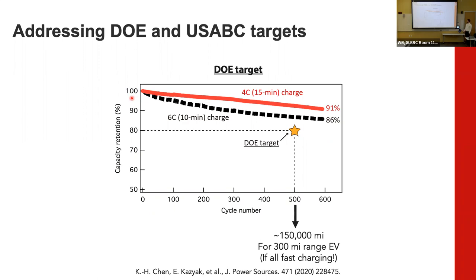And keep in mind that 500 cycle mark there, for a 300 mile range EV, that's 150,000 miles of driving, so a long way. And that's assuming that it was all fast charging, which nobody is fast charging exclusively. Most people are slow charging most of the time. And then some 10% of the time you're on a road trip and you need to fast charge. Fast charging is by far the harsher circumstance. So you're going to be above this line in most circumstances, right?